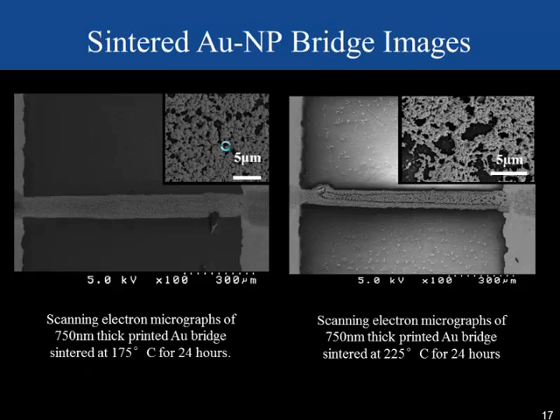These films were then imaged using a scanning electron microscope. What we observed on these films was a highly porous structure for both cases, which was very interesting, and as I hypothesized, it's due to the poor adhesive nature between glass and gold, which is well documented. One interesting thing, though, is that this highly porous gold presents a large surface area, which has potentially interesting applications for sensing.